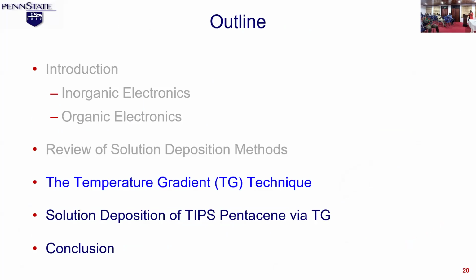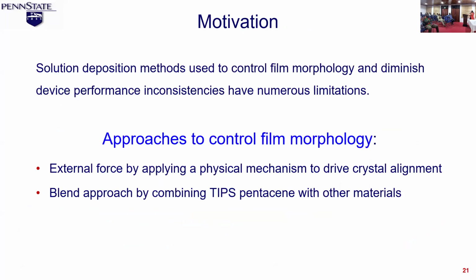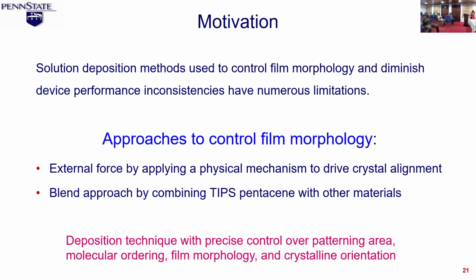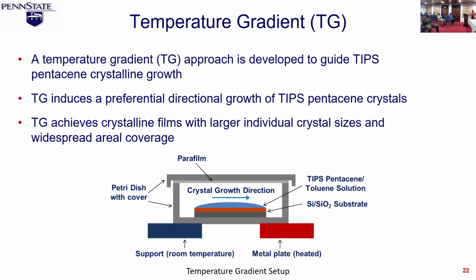So with these in mind, what I wanted to do was to come up with a method that would overcome these challenges, and that is what the temperature gradient technique is, right? The idea of the temperature gradient technique is to use a force to control the crystallization, the direction of it, and also the size of the crystals that we get. The second method, which is the blend approach, is an approach that people have used, and I ended up developing that on top of the temperature gradient method, and we'll see why. Right. So again, the technique here is to control how the crystals form. All right. So what is the temperature gradient method?